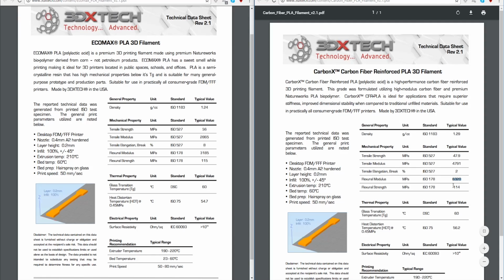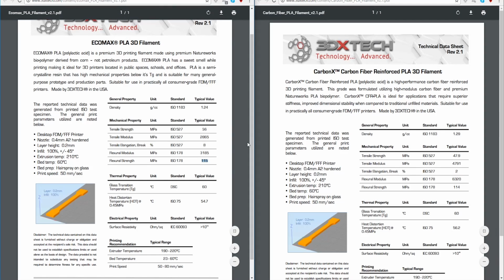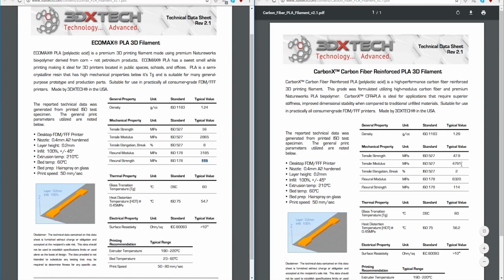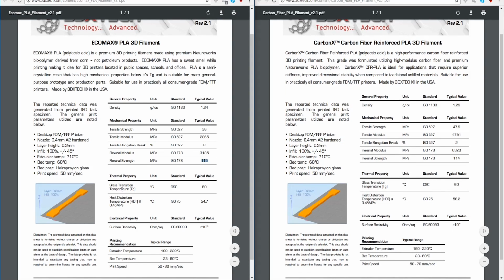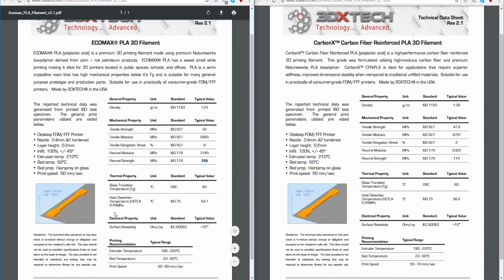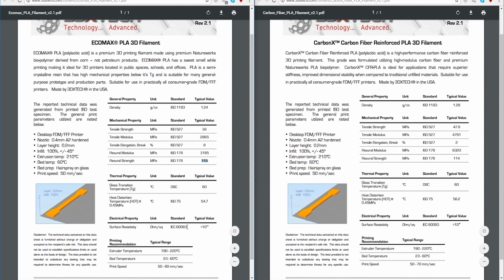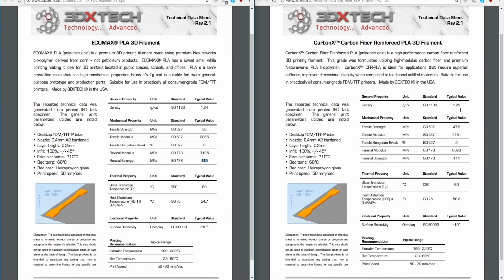And then finally, flexural strength 114, and you see that the flexural strength is now on par in bending with the PLA. So we'll actually almost beat out PLA in flexing, compared to its tensile strength, which was quite a bit lower. So very, very good in flexing, extremely stiff material, but extremely brittle material. So this is very interesting. And then we see the glass transition temperature didn't change much, 60-60. Heat distortion temperature at 0.45 megapascals pressure is 56.2, 54.7. And the density changes 0.05 grams per cubic centimeter. So very interesting, a little bit more dense.